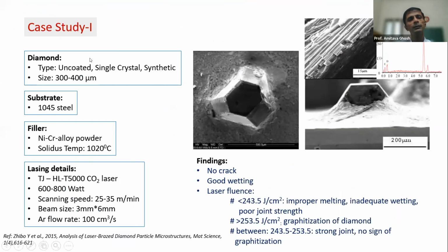Here, it has been attempted like a 300 to 400 micron crystal was based on a 1045 steel, same nickel chromium alloy that we are using for the furnace brazing. The temperature of the brazing is 1020 degrees centigrade, and here a CO2 continuous wave laser was used. And finally, it has been observed that there is no crack, in spite of the nickel chromium alloy being used, and wetting is pretty good.